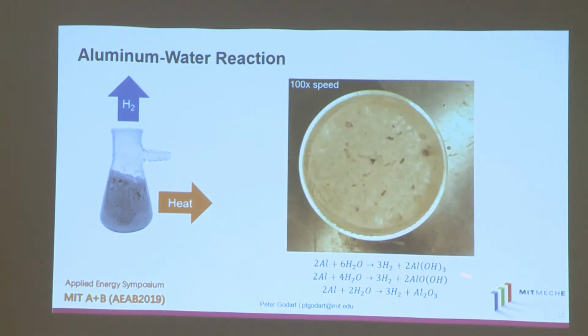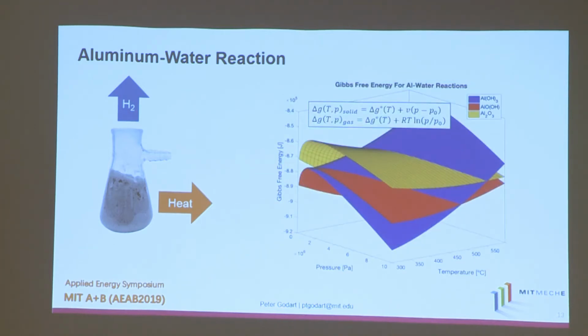And there are a number of reactions that can possibly happen that combine aluminum and water to produce hydrogen and then either aluminum oxide or some other hydrated aluminum oxide. And it's important to know which one of these reactions is occurring. So recently we've figured that out. And it's basic thermodynamics where you can determine the favorability of a reaction by looking at the Gibbs free energy of that reaction. So we can plot the Gibbs free energy for the different candidate reactions. And we know that that's going to be a function of pressure and temperature. And so the lowest change in Gibbs free energy across those different reactions at a particular temperature and pressure tells us the most favorable reaction to occur at those conditions.